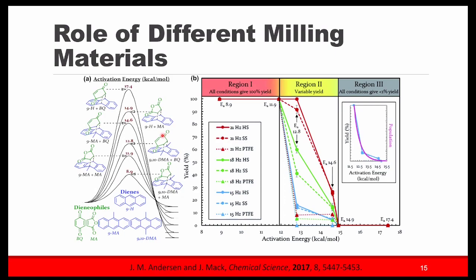And then what they do is they mill it for a certain amount of time, and they're looking at the activation energy versus the yield. And so when these processes have low activation energies, they're getting 100% yield. But then for some of the reactions, they're only seeing partial conversion in, I think, the 30 minutes or the 1 hour time frame of milling, and then eventually leading to no conversion. But they went further with this, and they started looking at different materials like PTFE here, Teflon, or stainless steel, and at different milling frequencies.